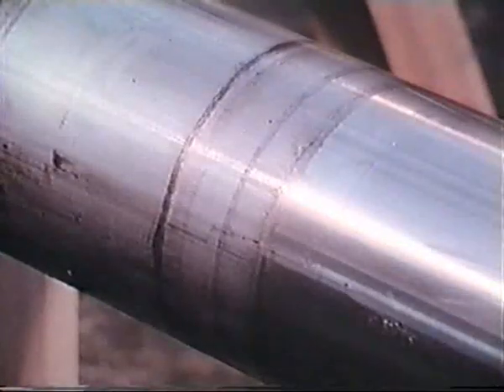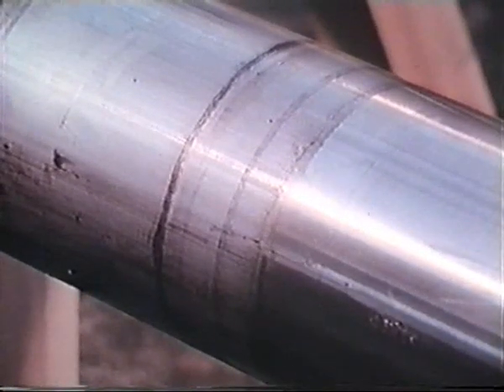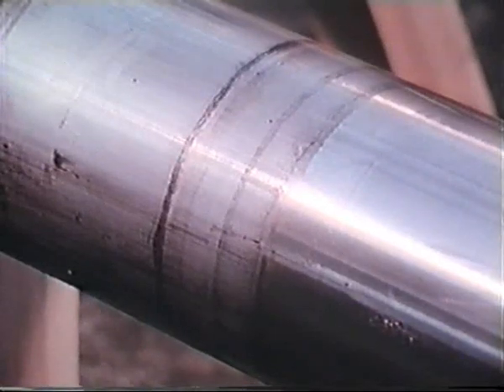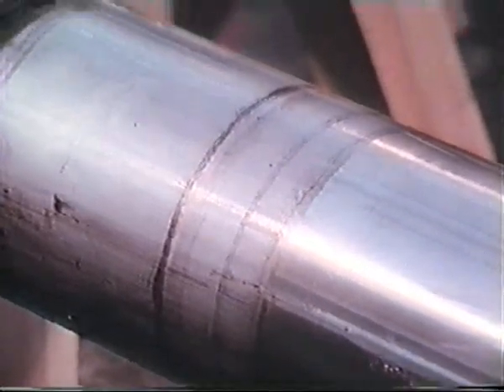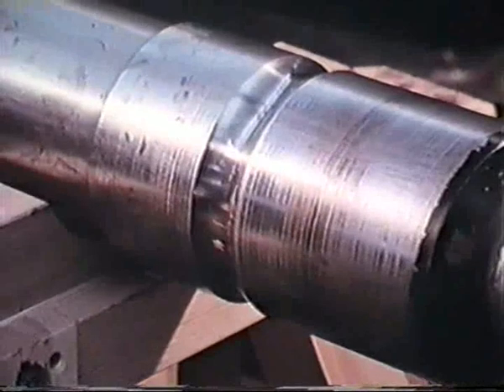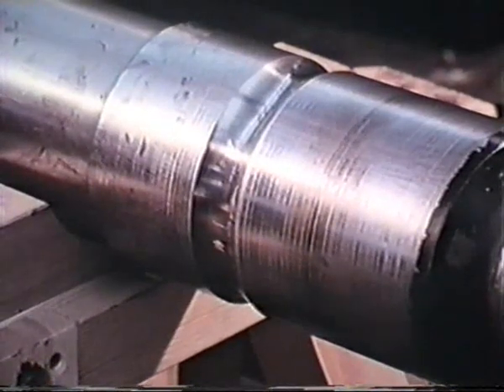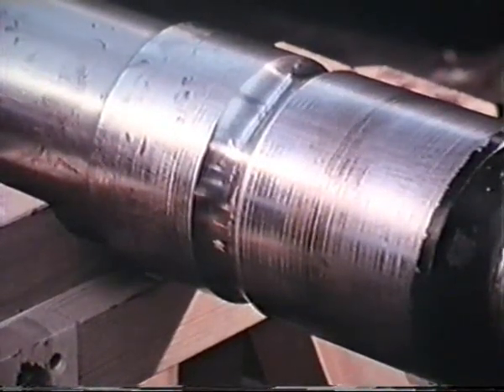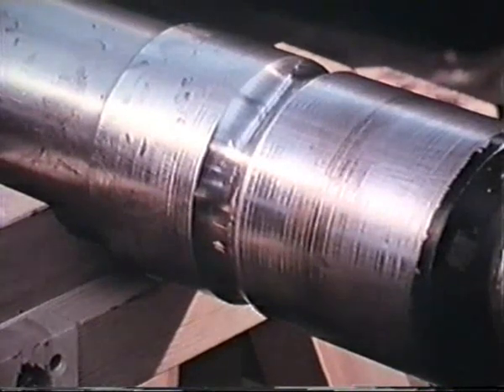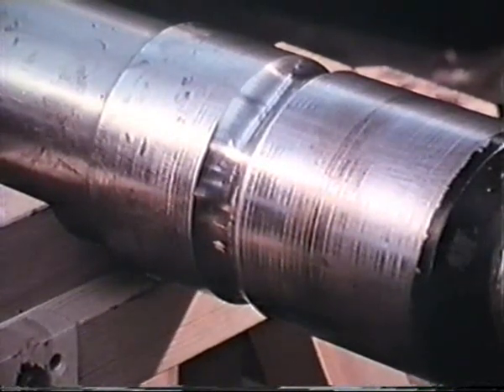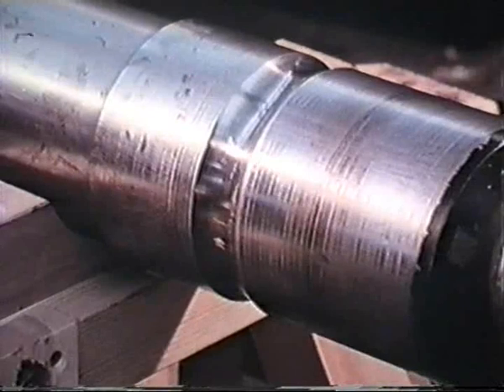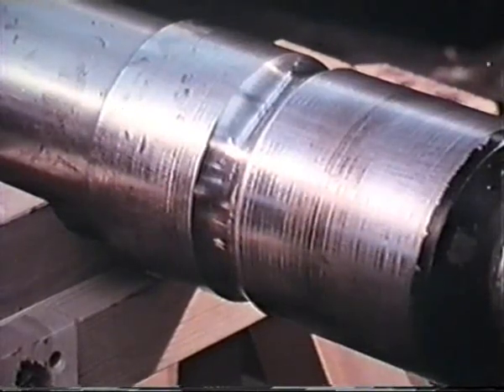The remedy lay not in changing the material or trying to exclude the atmosphere, but in design. By simply machining a groove in the axle, the high stress moved there and away from the area of the wheel, and the fretting corrosion was reduced. There have been no cracks after 1 million kilometers.